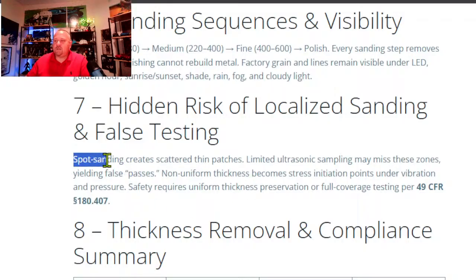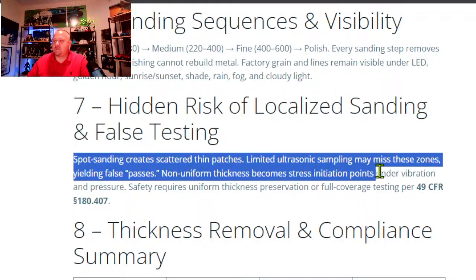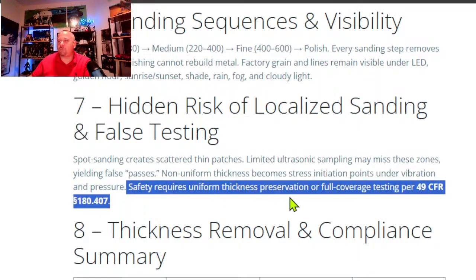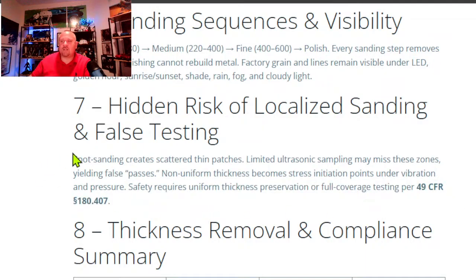Hidden risk of localized sanding and false testing. Spot sanding creates scattered thin patches. Limited ultrasonic sampling may miss these zones, yielding false passes. Non-uniform thickness becomes stress initiation points under vibration and pressure. Safety requires uniform thickness preservation or full coverage testing. 49 CFR 180.407. So let me read that again, and we're going to explain this.